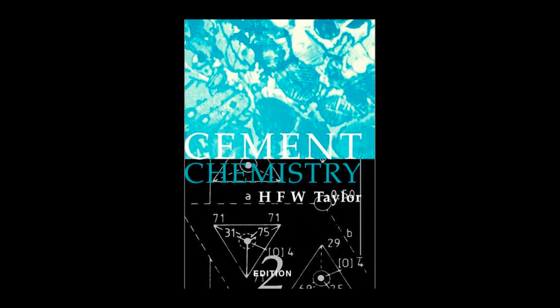Okay, what's first? First, you have the unreacted grains. These are the brightest phases, typically alite or ferrite, which just haven't fully reacted yet. Second, calcium hydroxide, CH. This appears slightly darker than the unreacted phases, and it tends to be either massive and crystalline in large voids or finely dispersed throughout the paste, especially in low water-cement ratio mixes.